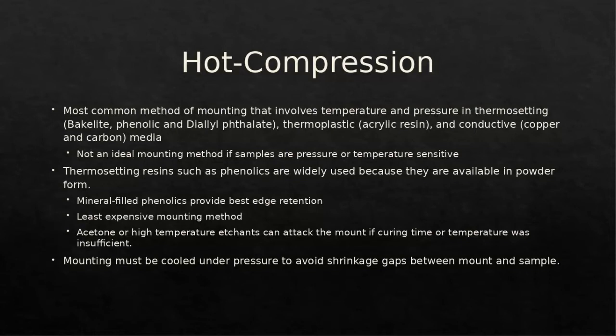I'm typically operating anywhere between 95 to 100 psi, and the temperature of the media that I use is 200 Celsius. So with low melting temperature materials, where you're looking at 0.4 of the melting temperature and that falls below that, I would essentially be hot working and or annealing my sample. So that's not good. Since I'm already altering the microstructure, I will not be able to correctly identify the true structure of that component.